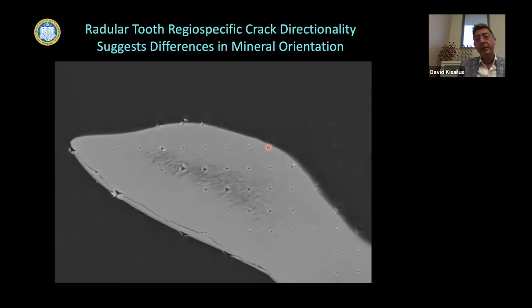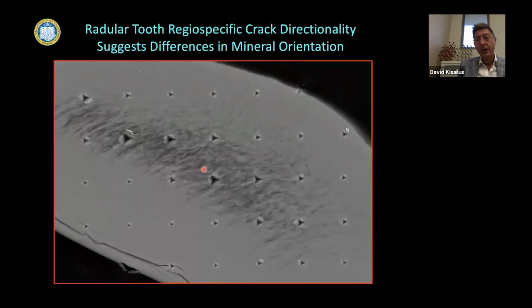And so we've done some, I mentioned the nanoindentation, taking a closer look at these cross sections where you see the indents in the core region and the shell region. Obviously, the softer component has the larger indents. If we take a look at the shell region where the smaller indents are, we see cracks, but the cracks propagate along the periphery of the tooth. So we were curious as to why that was happening.